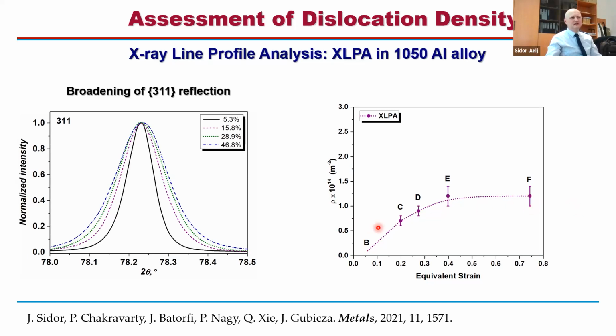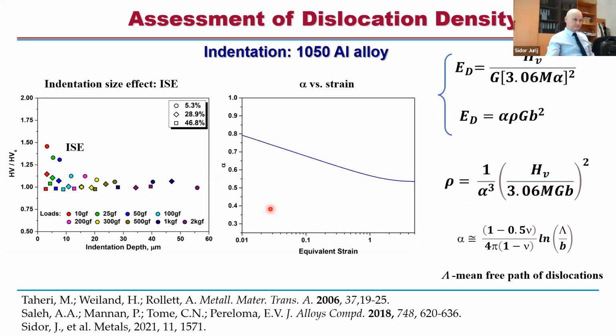And then the question is to what extent these results are reliable or not. Self-evidently, you compare with the results of other researchers, and we have seen very comparable results. And then we said, okay, let's try to estimate dislocation density by other techniques, and one of them is indentation. So when you do micro hardness measurement, you can do it with different loads, starting typically from 10 gram force up to 2 kilogram force, right?